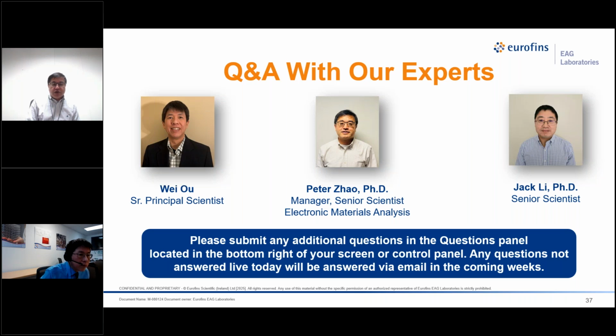But sometimes we have to trade off something. We may lose depth resolution, or we may have a high detection limit for a small area. So it depends on what type of device. It relates to the surrounding area, the material in the surrounding area, and the detection limit may be high. Technically, yes, we can analyze very small areas; the smallest will be 1 to 2 micron. Okay.